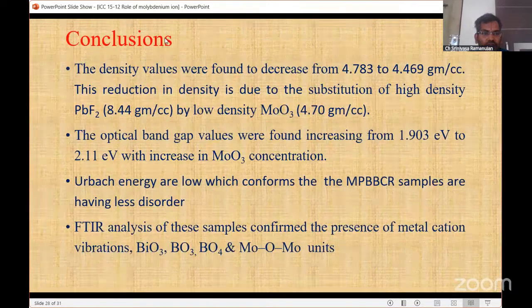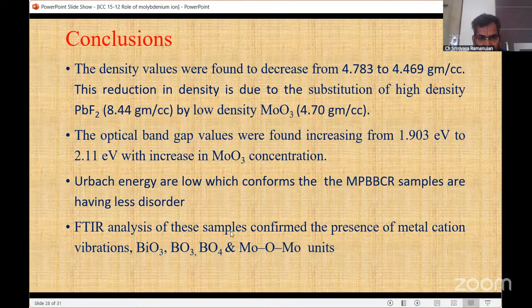These are the conclusions. The density values decrease from 4.7 to 4.4, due to the replacement of lead with molybdenum. The optical band energy gap increases from 1.9 to 2.1 electron volts with increase of MoO3 concentration, and the Urbach energy is very low, indicating less disorder. FTIR further confirms the metal cations and BO3 and BO4 structures.